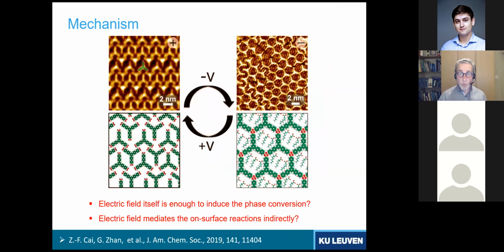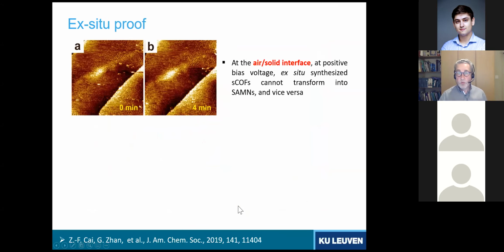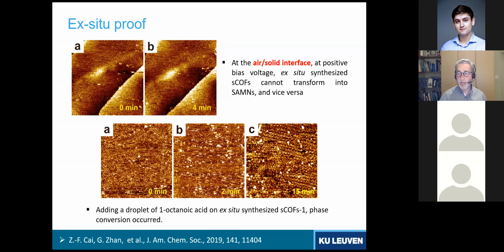And of course, what is the mechanism of this? It's something that we're still working on, actually. But there are a few questions that one could ask ourselves. Is the electric field by itself enough to induce this phenomenon? Well, some control experiments teach us that it does not work at the air-solid interface. So if you remove all solvent and try to polymerize or depolymerize, it doesn't work. You need a solvent such as octanoic acid.